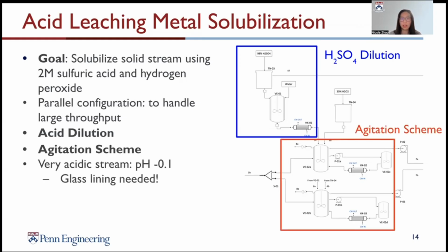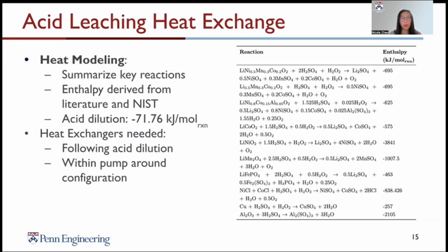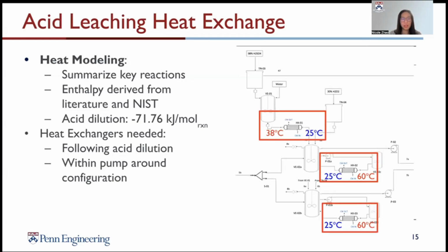We designed a unique agitation scheme with a pump-around configuration to handle our mixing needs in this process. And because of the very acidic conditions, glass lining is utilized for corrosion resistance. An important part of acid leaching is modeling all of the heat that is released during this process, and we have summarized the key reactions during the step on the right. Enthalpy for each step is derived from literature and NIST databases, and acid dilution also generates a lot of heat. Because of this, heat exchangers are needed to handle the heat generated following acid dilution and during the mixing pump-around configuration.